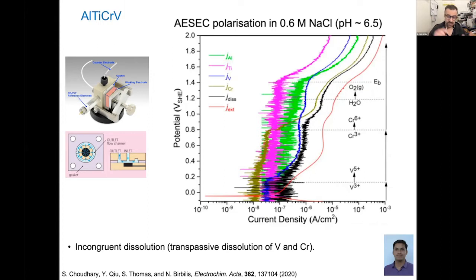So it's quite clear, again, I'm going to cut a long story short, that we get incongruent dissolution. So that means non-stoichiometric dissolution of this particular alloy as you polarize it. What you see on this curve is the red solid line, which is the current that you measure from your potentiostat, and these other lines are the contributions that come from titanium in pink, aluminium, vanadium, and chromium, and the total dissolution current measured by, in this particular case, the spectrometer in black. So it turns out that you get more dissolution of vanadium and chromium in the system, and then their transpassive dissolution actually occurs at some rate, significant relative to the other elements, because this is a log scale.